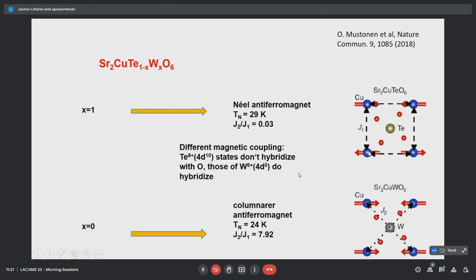Up or down, to the right, to the left. So that's dominant. The next nearest interaction, that's J2, that would be across here. That's small against J1, which is this interaction. Now, if you go to the other side, to the tungsten compound, it's just the opposite. There we have a dominant next nearest interaction, and this will result in a so-called columnar antiferromagnet. Here, these two are in one direction, these two are in the other direction. Why is that so different? That comes from a different kind of hybridization. The tellurium states don't hybridize with oxygen, whereas the tungsten, they do hybridize. So now the idea for sure is, what happens then if we mix the two and we are just in between?